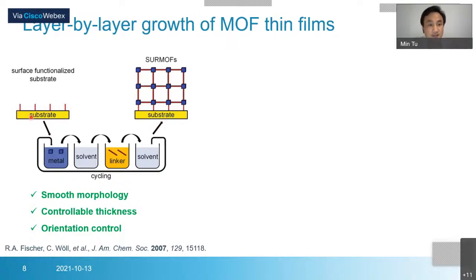So we first functionalize the substrate, for example, silicon or glass, to have the self-assembled monolayer on the surface. Then we alternately immerse it into the metal solution or the linker solution. Then we use solvent to rinse off the unreacted component. By repeating this procedure many times, we can have the MOF film on the surface. By using this method, we can have a smooth morphology, and we can control the thickness by controlling the deposition cycles, and we can even control the crystallographic orientation.